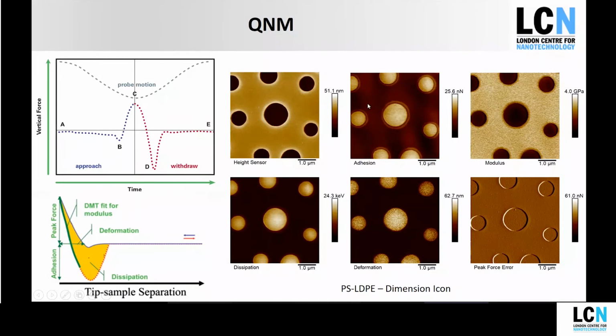So we can achieve these maps. This is just the height map. Then we have adhesion. This is a polystyrene LDPE sample. You expect LDPE to be more sticky, which it shows. And this is the modulus here. You expect LDPE to be a lot softer than polystyrene, which is there. And then we've got dissipation and deformation. Obviously, LDPE would deform more than the polystyrene.